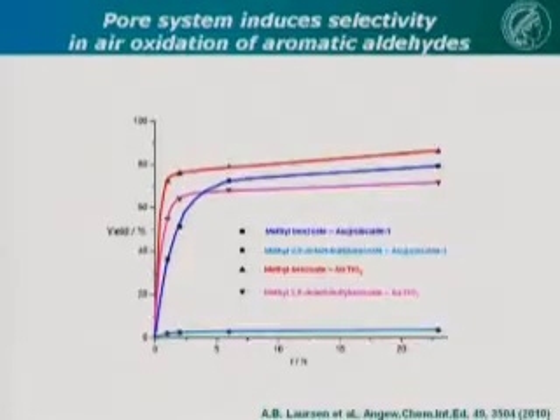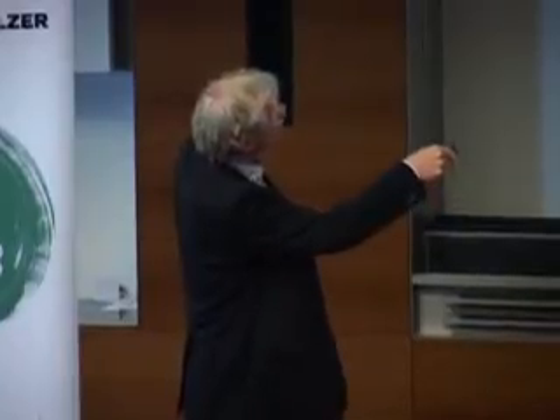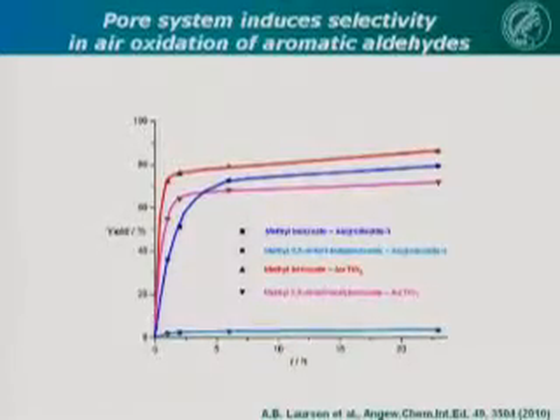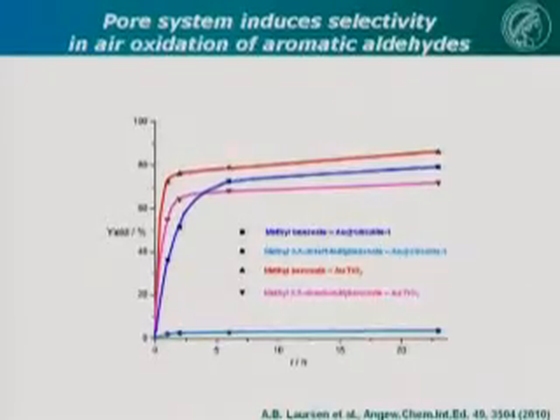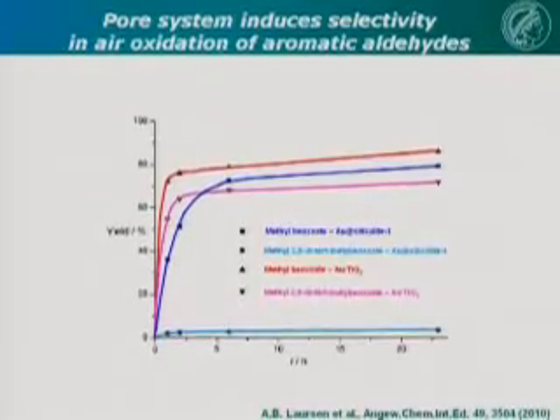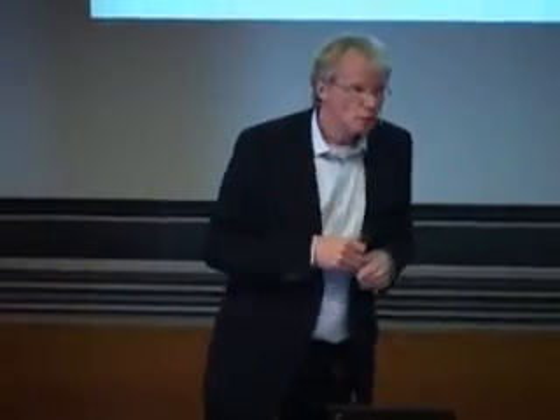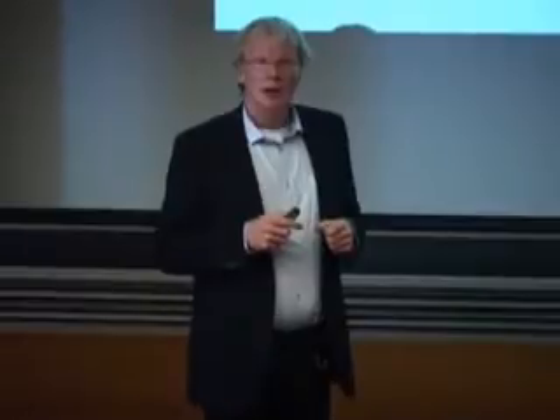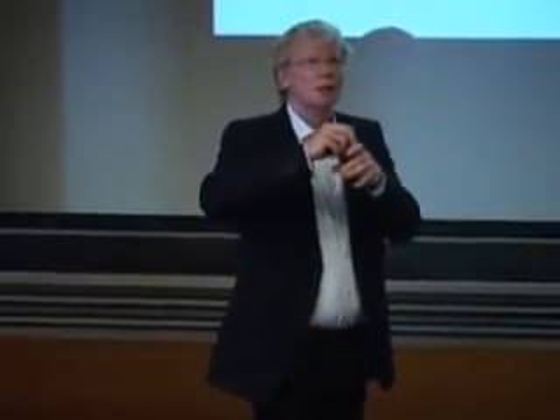If we have the gold on the inside of the zeolite, where only the small molecule can reach the gold particles, but the big bulky reagents cannot enter the zeolite pores, the small methyl benzoate is converted like on the gold on titania catalyst. But this bulky substrate cannot enter the zeolite, can never reach the gold particles, and thus we do not observe any conversion here. So if you place particles protected by a pore system, you basically have sort of a molecular sieving effect like it is known for zeolites, and we achieve this in this case by incorporating the particles.